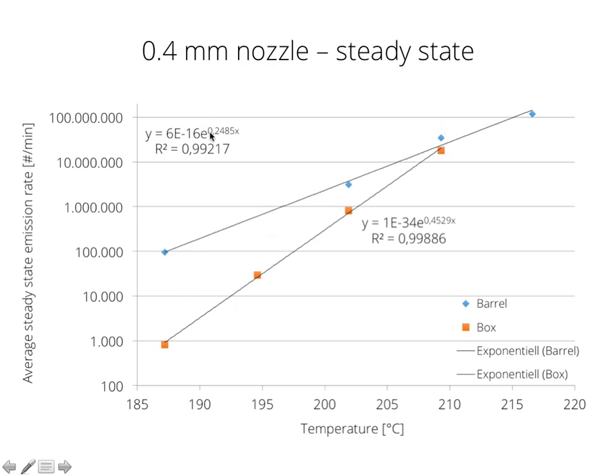We can see here that the logarithmic slope is not as high in the barrel as it was for the box. It could have multiple reasons. I'm not quite sure why we have such a low emission rate even in the barrel, because my extruder or my hot end was not clean, as it was inside the box. So it was my standard hot end that had some contaminated and burnt-off filament on there, but I did not have a failed print in quite a while, so maybe this residual polymer on the heater block had already burnt off, and the hot end itself did not emit a high amount of particles.